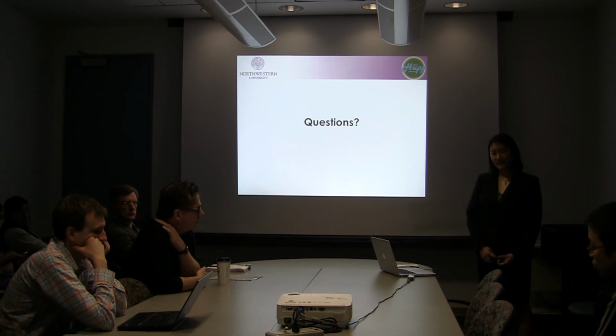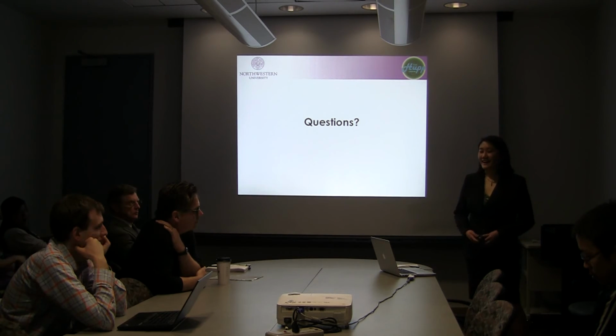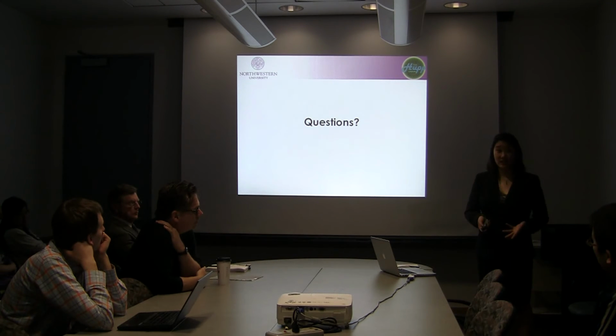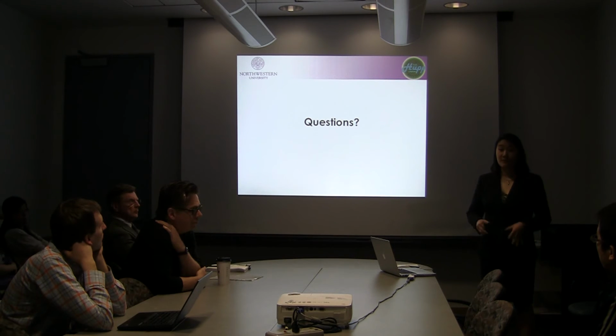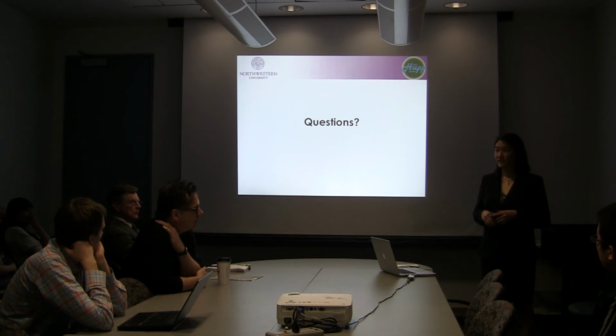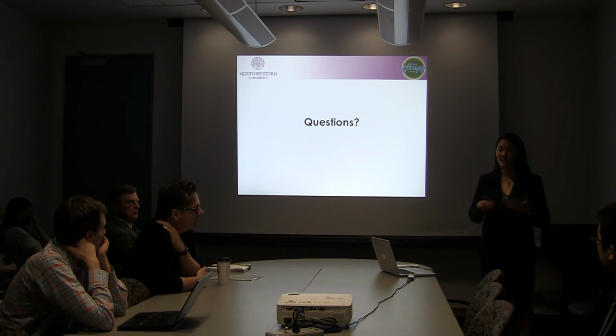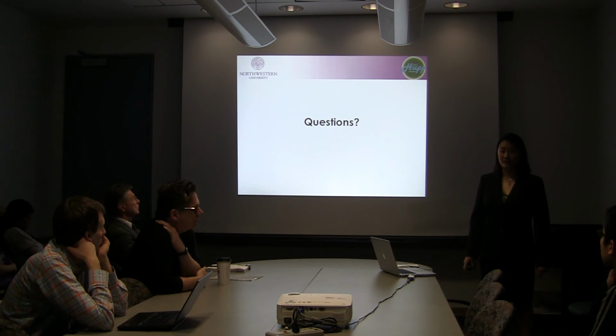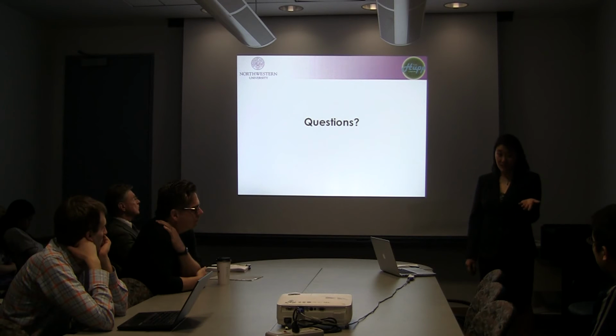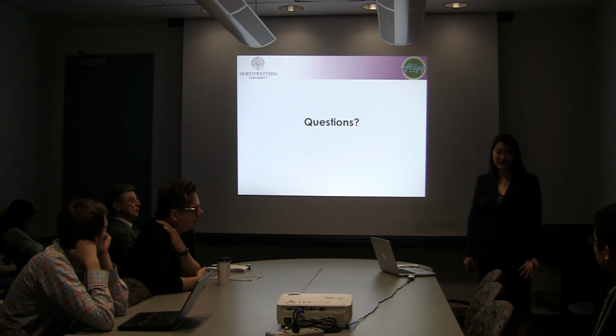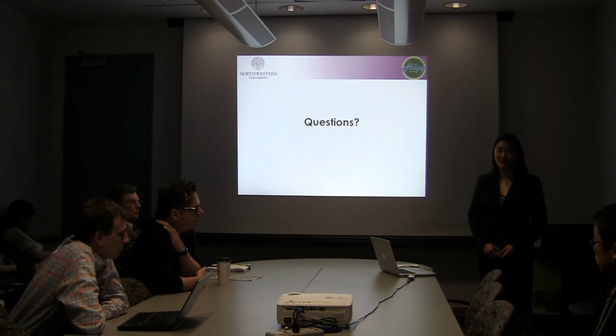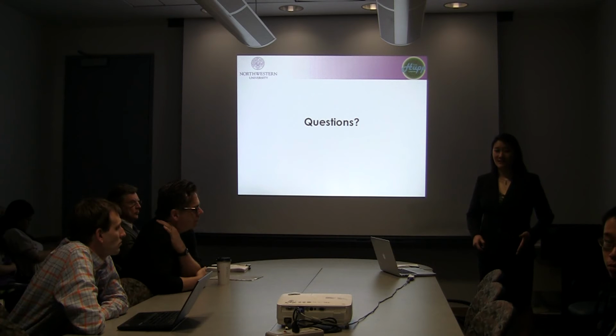It'll take too long? Yeah, the one limitation of layer by layer growth is that it's a very slow process, which is typically why I don't grow 300 cycles. That would probably take more than a week to do. For the purposes of my measurements and experiments, at least 10 to 15 cycles of growth is needed to do very simple UV-vis absorption measurements and thickness measurements, just to check what's actually deposited on the surface. Conceptually I could definitely grow up to 300 cycles of film, but that would take a very long time, and I haven't thought of something that I would need to do with that yet.